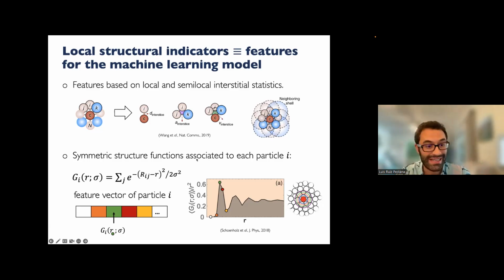Another set of functions that you can calculate is these symmetry functions. They are close, if you want to think about it, to a radial distribution function. So they are functions that are related to that. They are symmetric in space, and they basically measure the relative density of other particles with respect to the particle that you have. So you can measure these things, you can plot them, and you can gather a numerical vector with that information. So again, that gives you information about the local structural environment of a given particle.